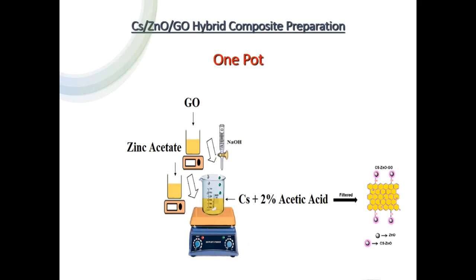For chitosan zinc oxide graphene oxide nanocomposite, we prepared 2 different samples with 2 different methods, casting as mentioned previously, and the one-pot method. The one-pot method was used by combining dissolved chitosan, dissolved zinc acetate, and dissolved graphene oxide as a mixture, then adding sodium hydroxide drop by drop to achieve a pH of 10.